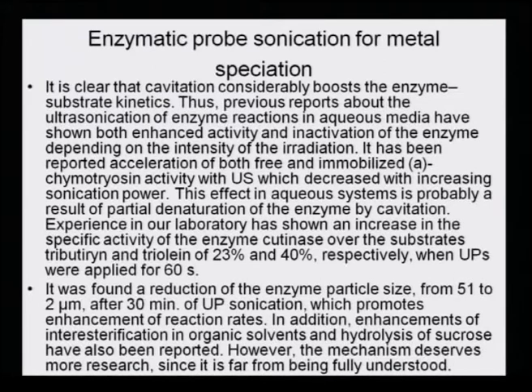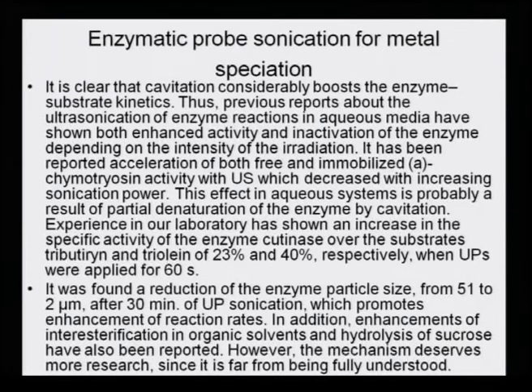Experience in our laboratory has shown an increase in the specific activity of the enzyme cutinase over the substrates tributyrin and triolein of 23 and 40% respectively, when ultrasonication was applied for just 60 seconds. A reduction of enzyme particle size from 51 to 2 micrometers was found in about 30 minutes of ultrasonication, which promotes enhancement of the rate of reaction. In addition, enhancement of interesterification in organic solvent and hydrolysis of sucrose have also been reported. However, the mechanism deserves more research and is far from being fully understood.